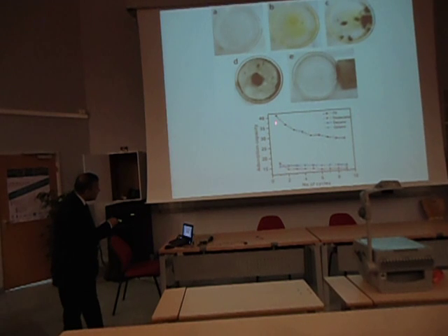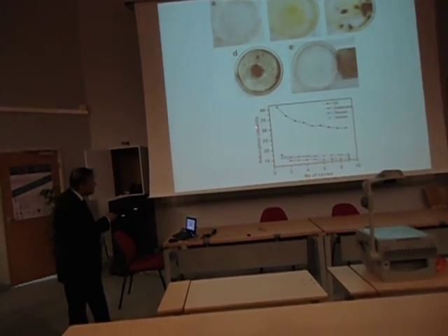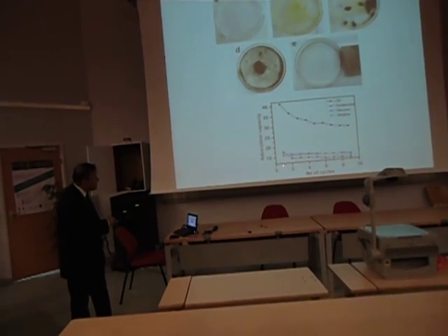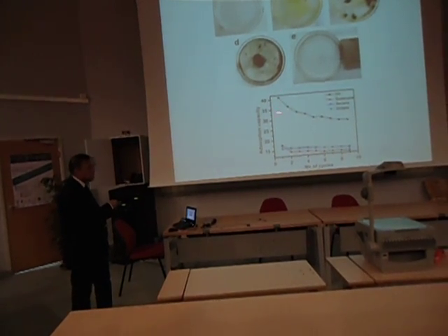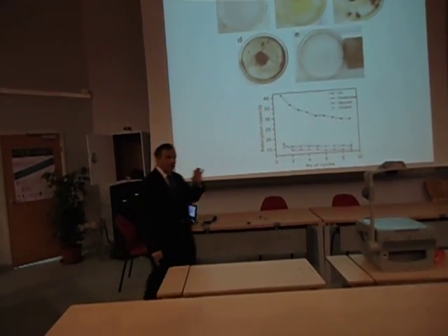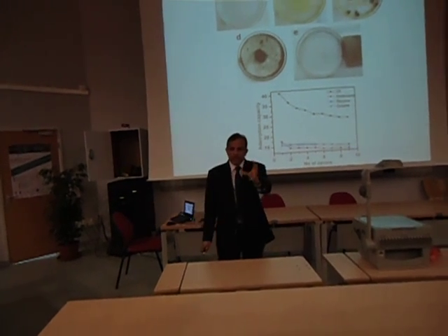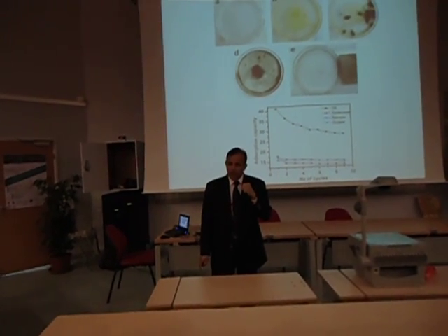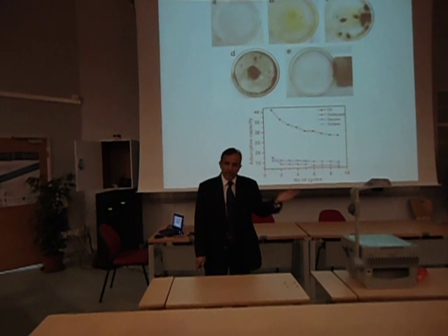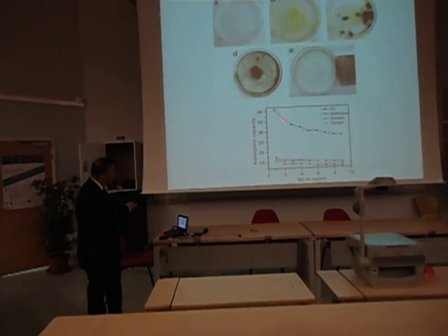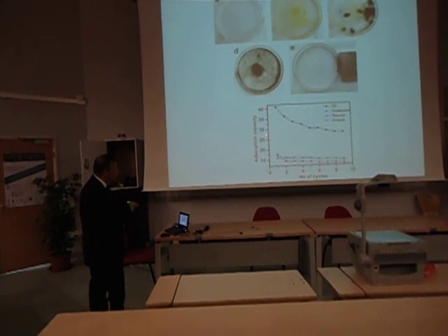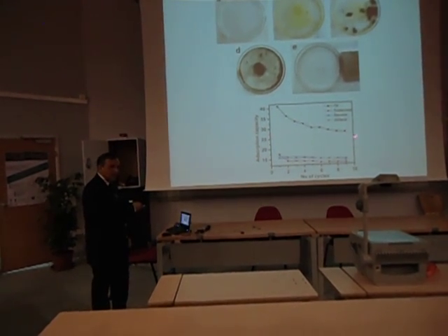And you can see that this is the absorption capacity. What it is showing is that in the first cycle, this particular carbon is absorbing 40 times its weight of oil. Then you recycle the oil, clean it back and reuse. Finally, over time, in equilibrium, you almost settle at like 28 times its weight that it is absorbing.